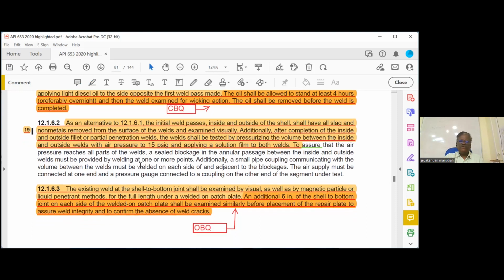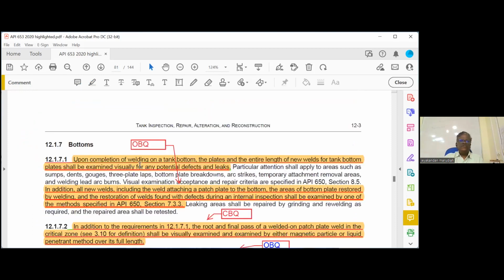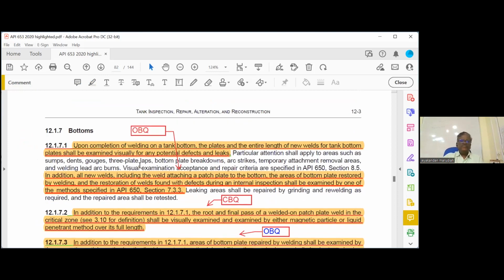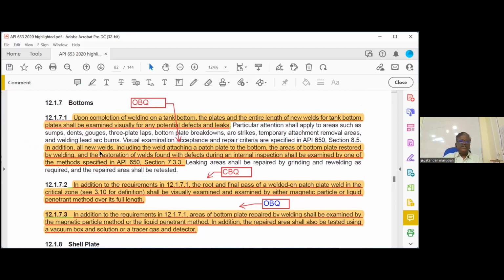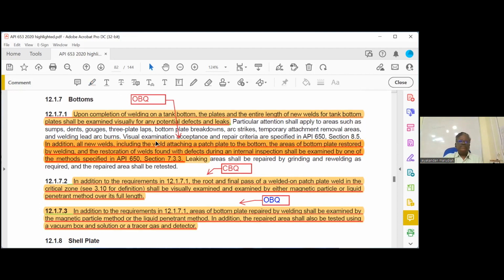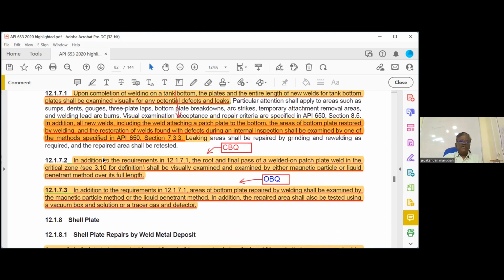Yeah, that is not important, because there are many requirements given. Now bottoms. Highlight the 6th line in the bottom. All new welds, including the weld attaching a patch plate to the bottom, the areas of the bottom plate restored by welding, and the restoration of found defects shall be examined by one of the methods in 7.3.3. So 7.3.3 means the vacuum box or other methods. Bottom check test. Then this is important. In addition to the requirements of 12.1.7.1, the root and final pass of the welded-on patch plate in the critical zone shall be visually examined and examined by either magnetic particle or liquid penetrant. Suppose in the critical zone you are using any welded-on patch plate, root and final pass you have to do MT or PT. That is important.